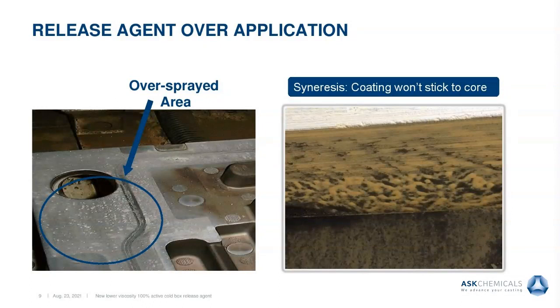Okay. And then the last question here is, is there a film forming time after application to the core box? So I'm inferring from that, after you apply it, is there a period of time you need to wait before you start your first core blow? No, not with 100% active release agents because the silicone does not evaporate. So however much you apply or put on the substrate, that's how much is going to be there. That's why you need to make sure that you atomize it properly, and you want to hold your spray tip perpendicular to the core mold or the core, and just go over very quickly one pass. That's all you need.